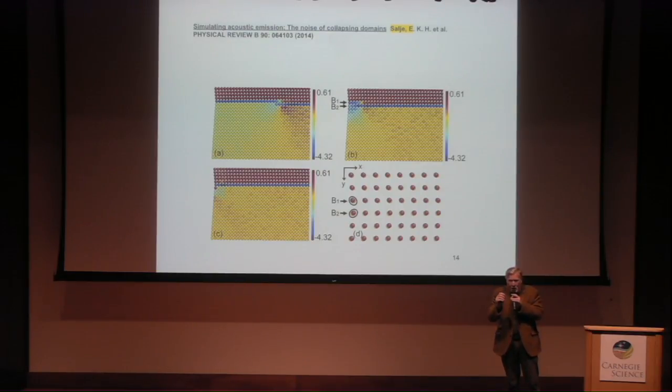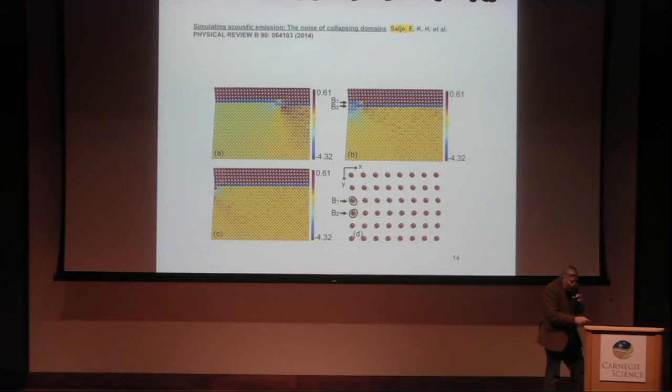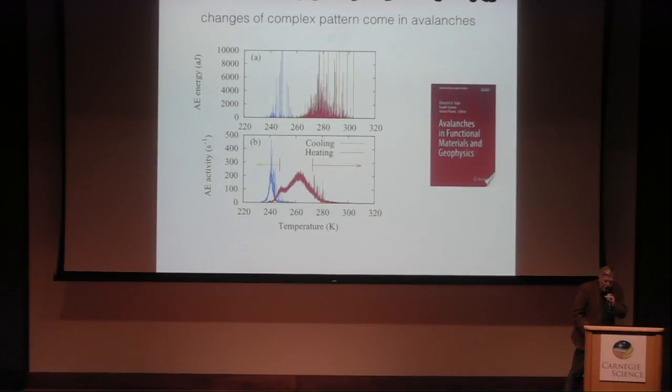So now you can measure the speed of that stuff by how often it hits the signal. I mean, you know where it starts in the middle, or somewhere in the middle statistically, it hits the surface, and then you know when it arrives. Now, I should say, this is a methodology which we have developed now for lots of other things. I mean, it's not just for ferroelectrics. We do it in particular for the collapse of porous material. You take porous materials, you compress it, then you have the same signal, the acoustic signal coming out.